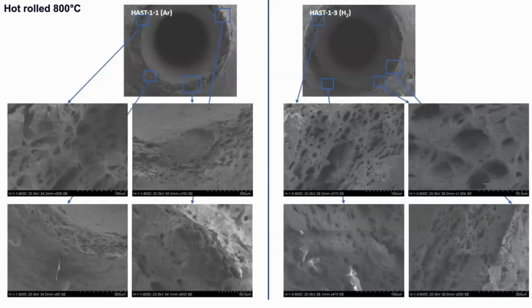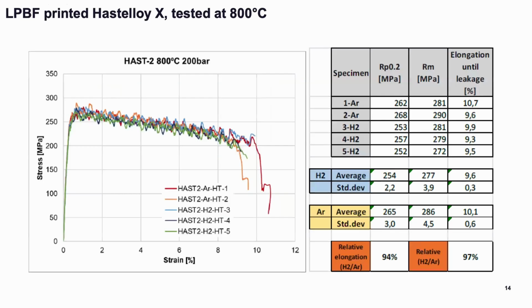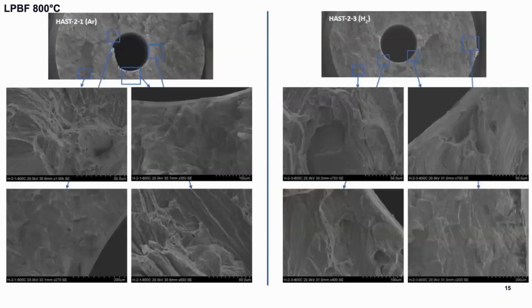The fracture surfaces are typical creep fracture surfaces with cavities. And for the printed material tested at 800 degrees, we have a much lower elongation to fracture compared to the conventionally manufactured material, both in argon and hydrogen. That is expected due to the completely different microstructure with the fine cell structures that we have. It's already considered when we design with this material, and the good news is that it doesn't get worse with the hydrogen. The fracture surfaces look quite similar to those in argon.